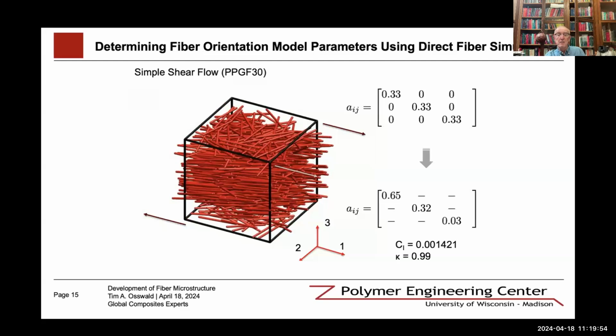You can see a final orientation in the direction of flow, and fewer orientations across the thickness of the part at 0.03. So that would be the lower tensor component.